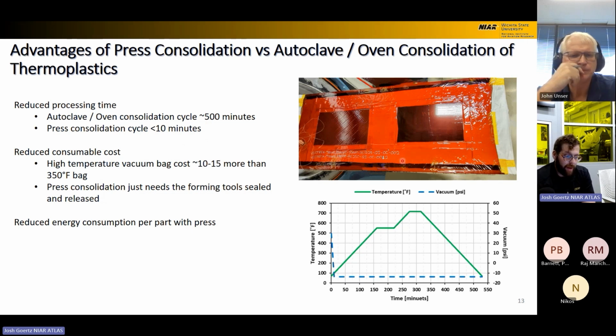There's also drawbacks with the vacuum bagging materials you need to be able to survive 750-degree air temps in the autoclave, and your bagging materials are extremely expensive, and they're also less forgiving than your traditional thermoset bagging materials. So you end up with a higher failure rate of your vacuum bags, as well as the materials themselves costing 10 or 15 times more to create that same vacuum bag. And they're also less forgiving of complex geometry, because the polyamide bags don't really stretch. And then there's also energy savings on a per part basis with how much less time you have to spend heating that volume.